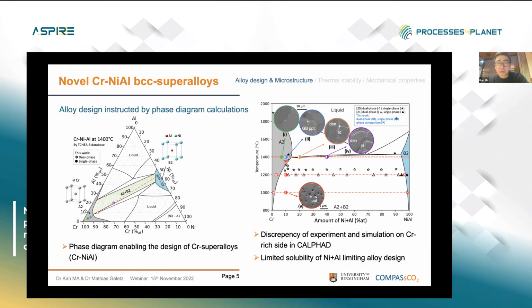And experimentally, we have demonstrated that this BCC superalloy design works in chromium, with the chromium matrix and nickel aluminide precipitate. But the issue is that, as you can see, the area of the single phase is quite small. And what's more, if we add a high content of nickel and aluminum, we form this grain boundary precipitate or dendritic microstructure, which is detrimental for the ductility.